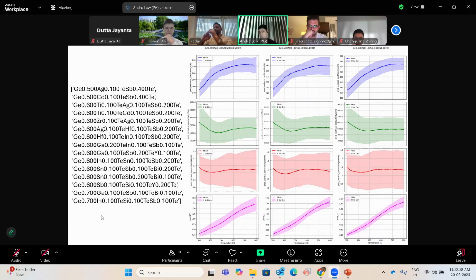Are you sure you have explored the latent space fully? Are there regions that are unexplored? There definitely will be compounds unexplored. We did not visualize the latent space for these compounds. But remember, we are just looking at germanium telluride as a start, because we wanted to be more discrete. There's nothing stopping us from going to the full latent space, but the latent space itself is huge. It is 512 plus 100 temperature, concatenated. So it may not be reasonable to do BO on this. But you could further reduce it with some PCA, and then optimize in the PCA space and do an inverse transform back to latent, something like this.